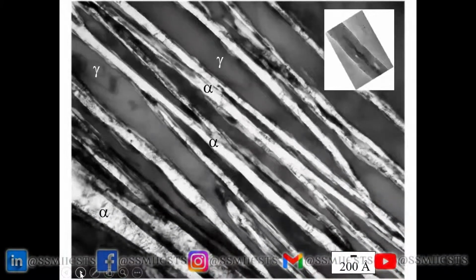this is the world's first bulk nanostructured material. It can be produced in thousands of tons, and it consists of these bainitic ferrite plates, which are only 20 nanometers in thickness, and they are actually finer. They are actually finer than the carbon nanotube that you see on the top right-hand side. Okay.